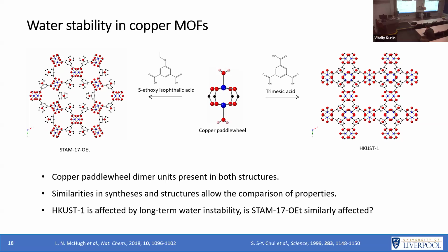Copper MOFs are good for certain things like absorbing gases like ammonia, but they're not very stable long-term to things like humidity. So if you're going to use them in an application like putting them into, I don't know, a gas mask filtration system, something needs to give. So that's why this new series of frameworks was developed, called the STAM series. And essentially they keep that same metal center, so this copper paddle wheel structure, but they change the linker. So we have this BTC, or I actually call it trimesic acid, for HKUST-1, and then we have a functionalized isophthalic acid linker to form our STAM series.